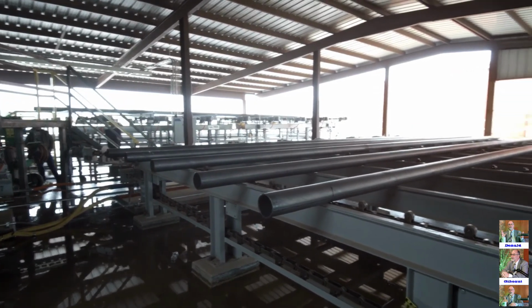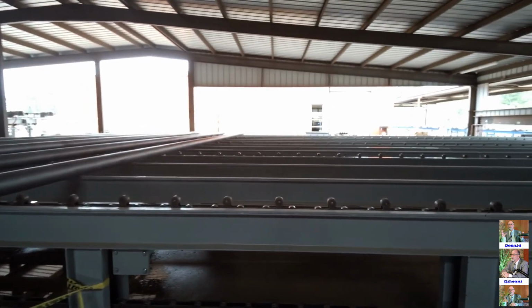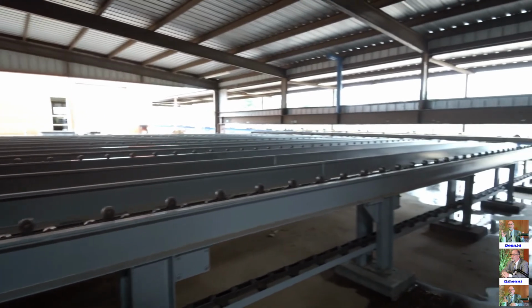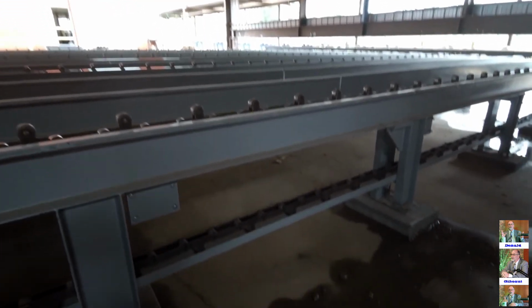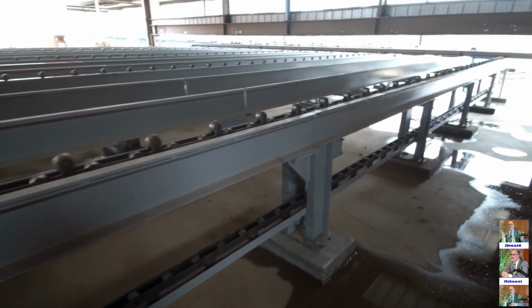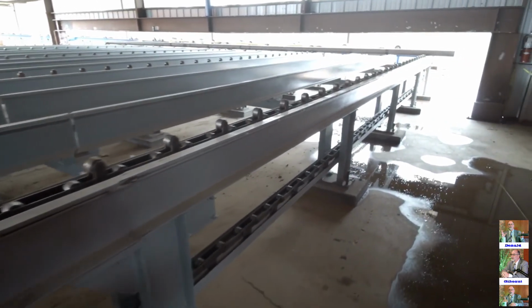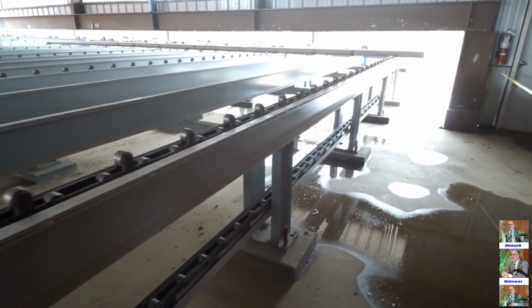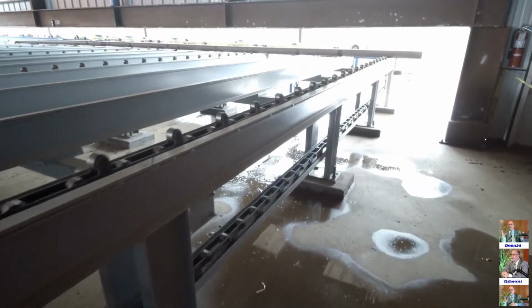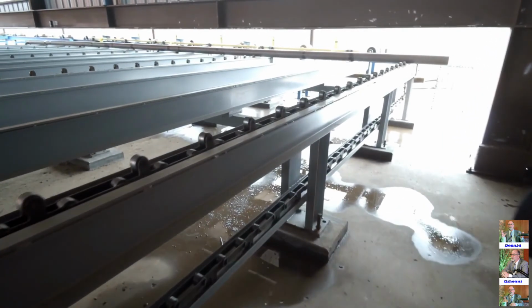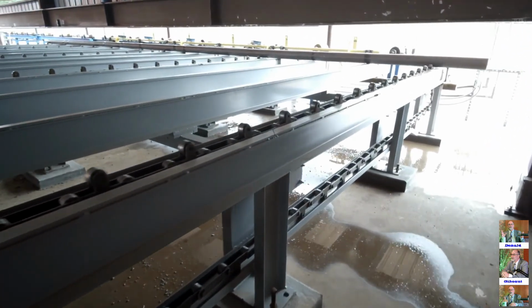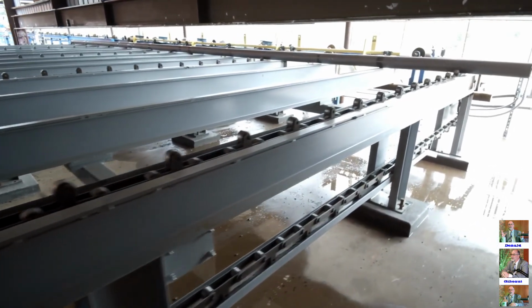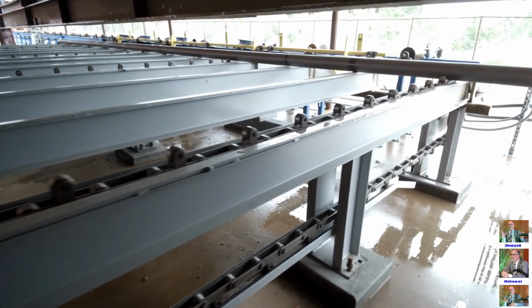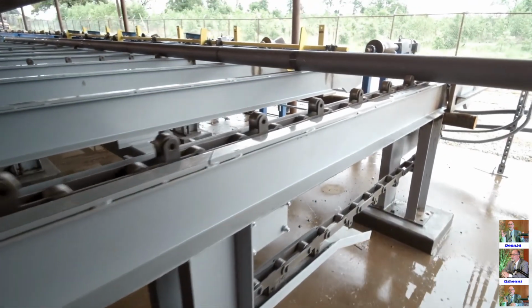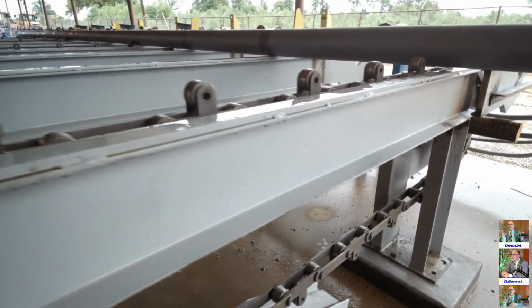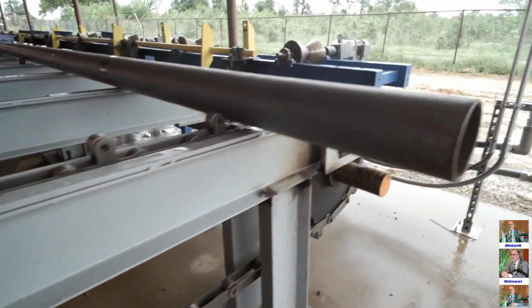And you know, there's quite a range of parts that run on this line. So going up the 7-inch, the pitch between these dogs doesn't keep it rotating 100%, but it's adequate enough to help on the smaller sizes control the straightness. A very simple drag chain design with quite a bit of supports in between the drag chains. Again, we're trying to help reduce the deformation and keep this pipe as straight as possible. So it rolls forward, comes down here to the end.